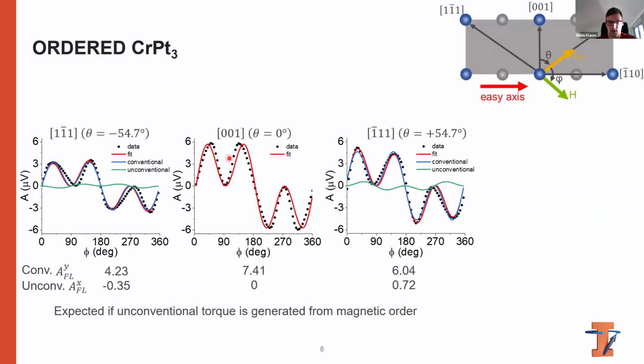So for 0 degrees, we see no unconventional torques, only conventional ones. For the negative 54.7 degrees, we see negative unconventional torques. For the positive 54.7, we see a positive unconventional torque. So this is what we would expect if the torque is generated from the magnetic order.